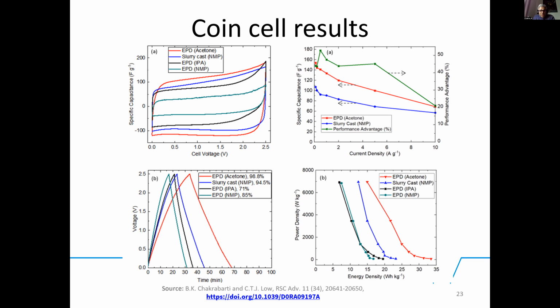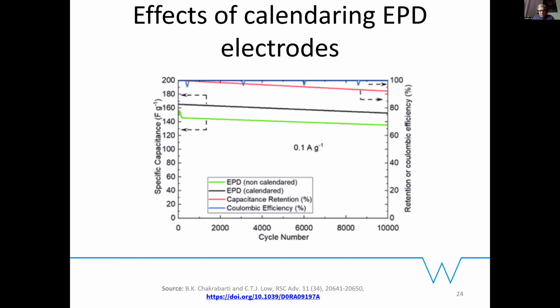Then from this, we decided to do cycling experiments at 0.1 amps per gram, comparing the standard EPD electrode with acetone without calendaring at the bottom and with calendaring at the top. So calendaring, or the hot pressing, was giving us higher capacitances and also better retention of the capacitance over 10,000 cycles. And these are still coin cell testing. So we thought, how would this perform when we scale it up, to form larger electrodes for pouch cell studies?